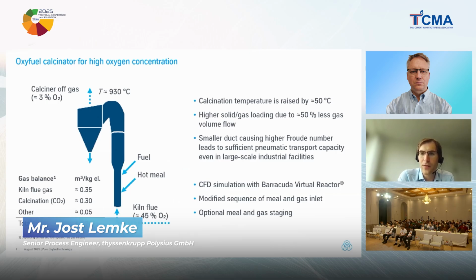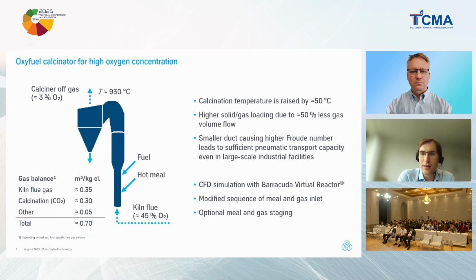However, due to the entrained flow reaction, all the combustion heat released from the combustion is directly converted into chemical reaction enthalpy in the temperature range about 900 to 950 degrees C. So despite the high oxygen concentration, it's also then feasible to run the calciner in the used temperature range due to the characteristic of the calcination reaction. The higher CO2 partial pressure causes a slightly raised calcination temperature. We expect something around 40 to 50 degrees C.